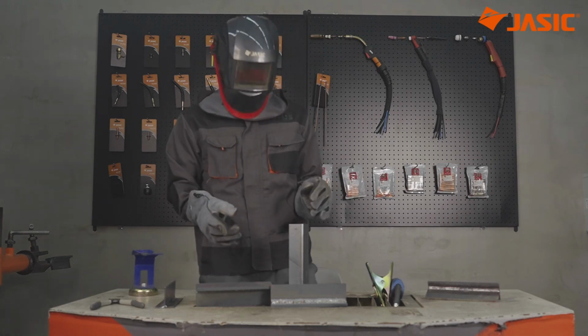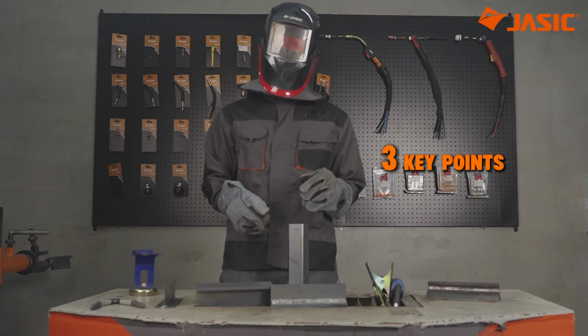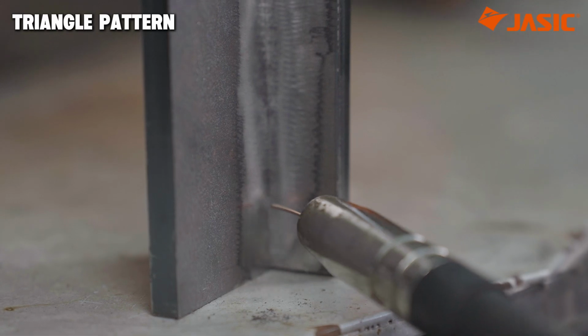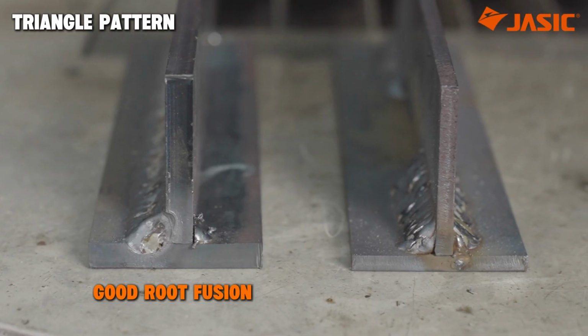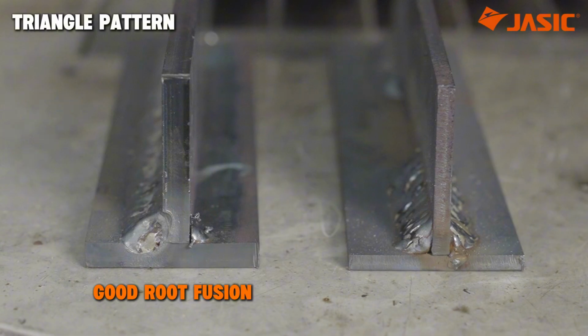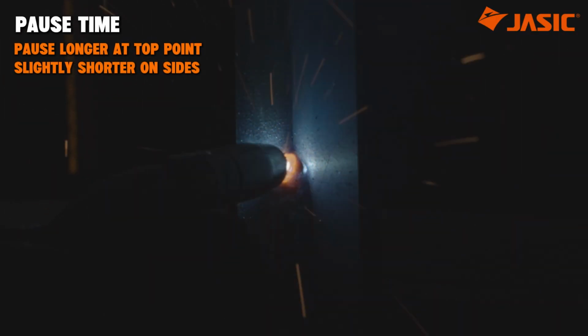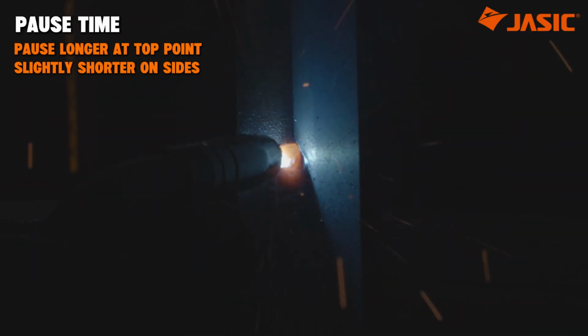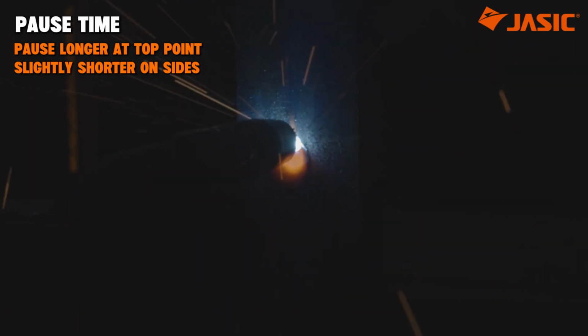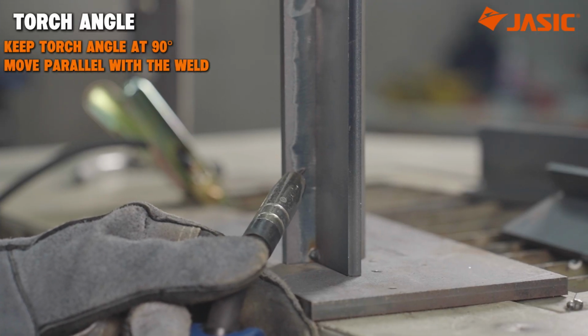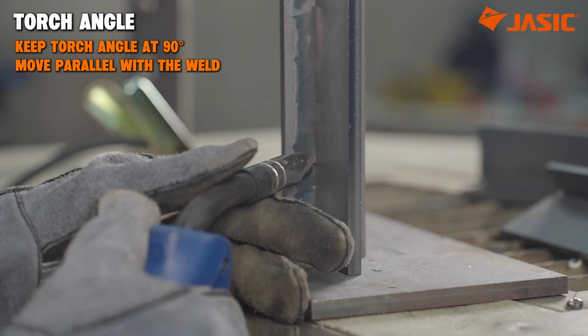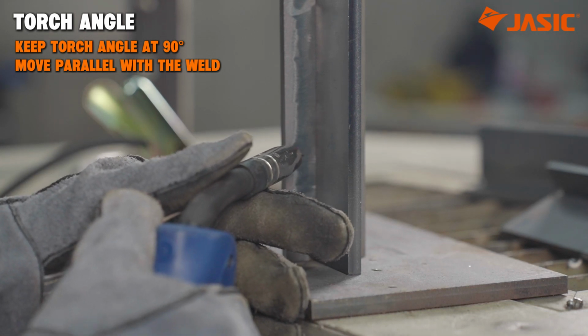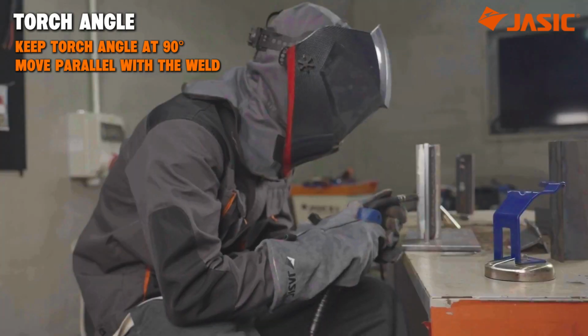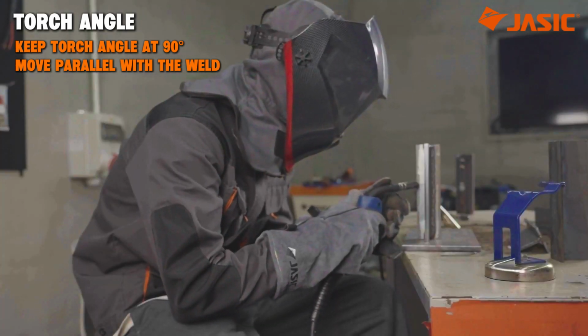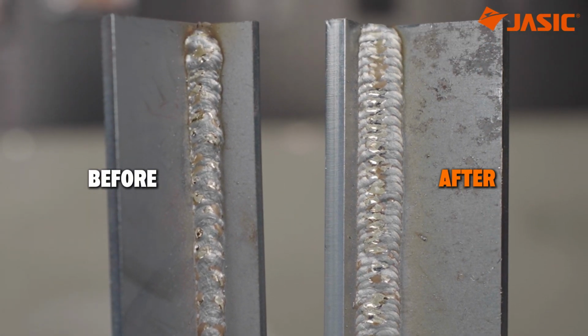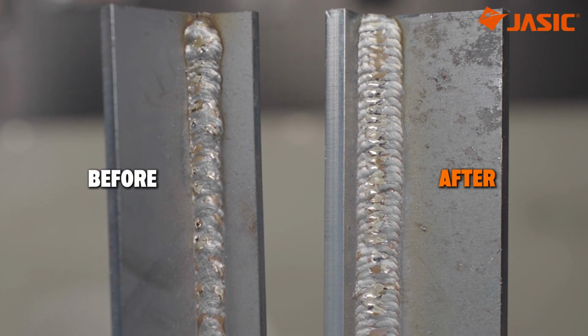Vertical fillet welding may look difficult, but these 3 key points can make a big difference. 1, travel pattern. Start with the triangle pattern. It provides good root fusion and gives you a finer, more consistent bead pattern. 2, pause time. Pause longer at the top point and slightly less on the left and right sides. Watch the molten pool and make sure the weld metal has properly filled the area. 3, torch angle. Keep the torch around 90 degrees vertically with only a slight downward tilt of about 5 to 10 degrees, preferably no more than 5 degrees. And remember to move your arm parallel with the weld as you move upward. Put these techniques together and you can get a vertical fillet weld that's much flatter, smoother, and more consistent.